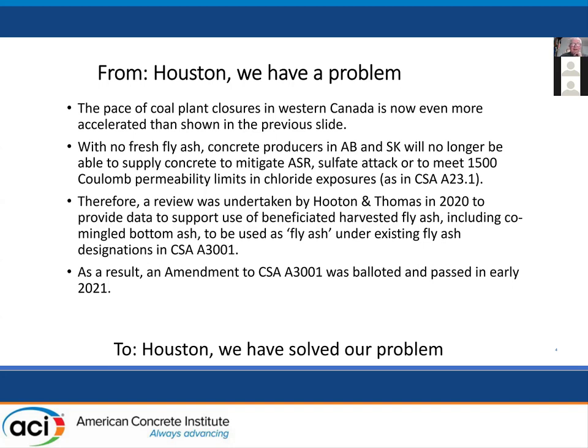So we undertook a study on behalf of the industry, Mike Thomas and I, last year, and we looked at all the literature data, and I'll show a tiny bit of it today, on using beneficiated ash. Now in Canada, almost none of the fly ash or landfill ash deposits are just fly ash. They're typically commingled with bottom ash. I think it's different than in the states in the US, but in Canada, they're generally commingled. So we had an issue here that if people want to beneficiate fly ash to replace the coal ash that will no longer be produced, we have to deal with this commingled ash. So we looked at that issue as well.